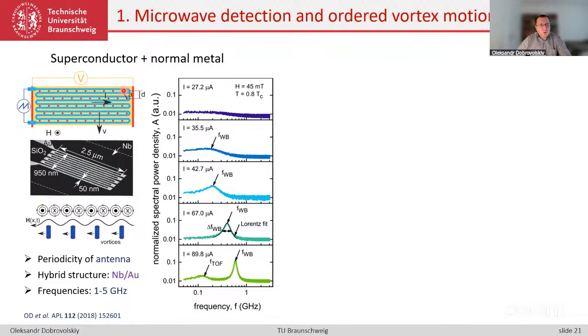Every vortex row corresponds exactly to one period of the antenna. This was needed so that all vortices would contribute in phase, and the entire signal would be just a sum of individual antenna periods. And then, by applying a current from left to right to the superconductor, the vortices were displaced from top to bottom in the plane of the screen. So vortices are looking at us, but moving from top to bottom.